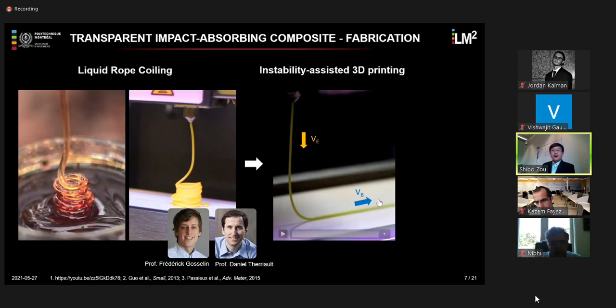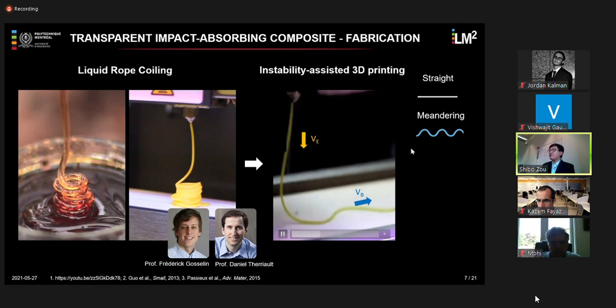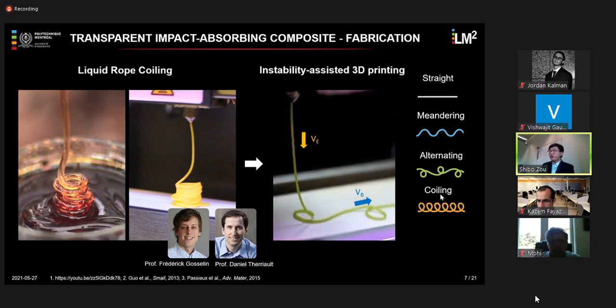As you can imagine, when the extruding speed of the molten polymer is equal to the moving speed of the horizontal plane, we will have a straight fiber, a straight pattern on the plane. But as we slowly decrease this moving speed of the platform, that is when the instability comes into play. We will have different patterns from meandering to alternating and to coiling, and finally the fiber with overlapping loops.